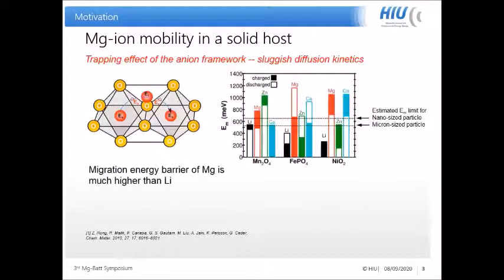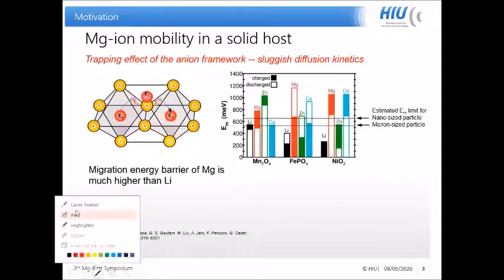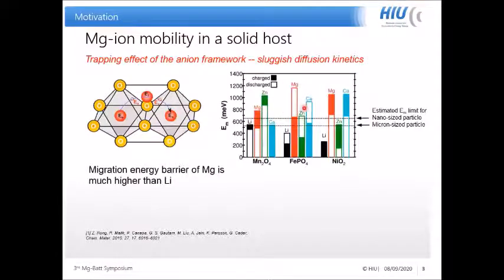Previously, Ceder's group calculated the ion mobility in some typical oxide materials or oxide hosts for lithium-ion batteries. And the result is that the migration energy barrier for magnesium is always much higher than that of lithium. And if we look at the values, all of them are actually even much beyond the estimated energy limit for ion mobility in nano-sized particles.